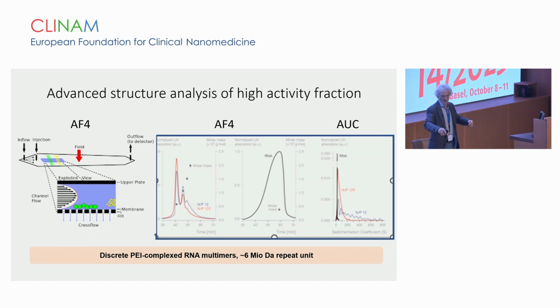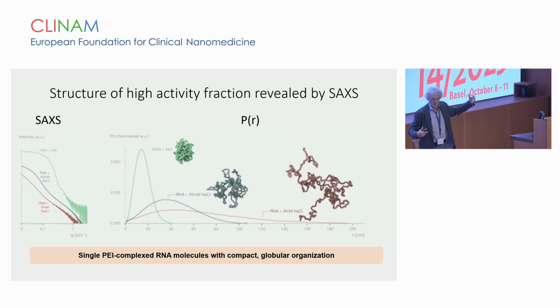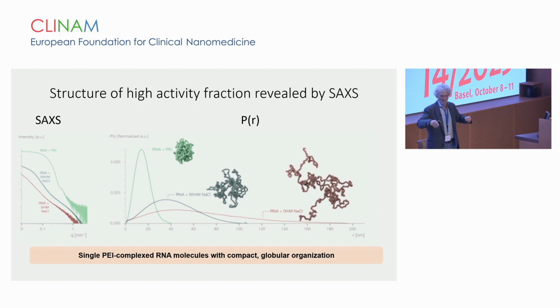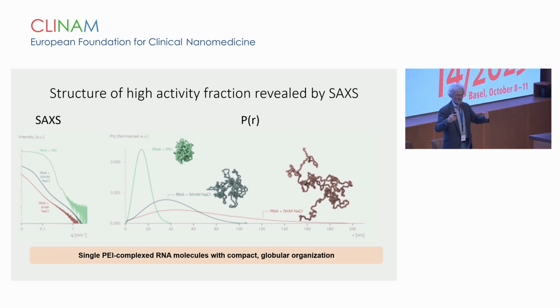That's again our AF4 method. And what you see is, if you separate according to size, you get different oligomers with repeating molar mass, which corresponds to something like a single mRNA complexed molecule. And so this means somehow we could now form a formulation where individual nanoparticles consisting of single RNA molecules exist. This has also been proven by X-ray scattering. You see the X-ray scattering curves to the left and what we call pair distribution functions to the right. What comes out is that the RNA is extremely compacted, very small, with certain advantages for delivery. You can now reach compartments which were not accessible so far, and you can functionalize and everything.